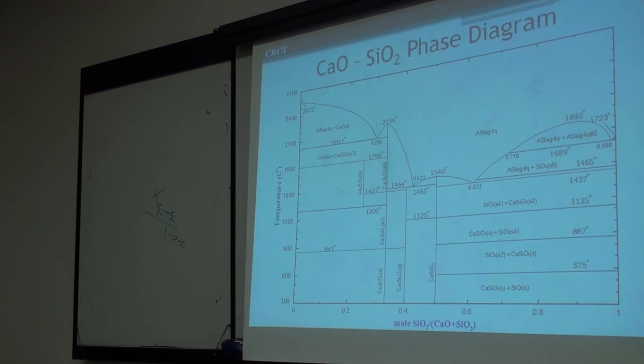So that's what I said. The phase diagram, if you didn't have it, you have the miscibility gap here because the ionic region and the molecular and covalent region don't like to mix terribly much. Here you do have some compounds. In this particular case, the orthosilicate Ca2SiO4 solid compound does correspond to the minimum.